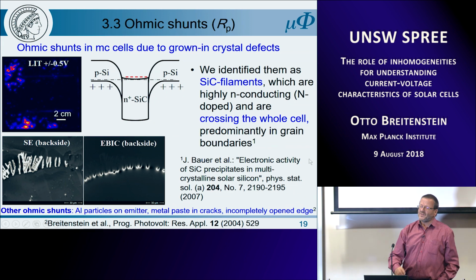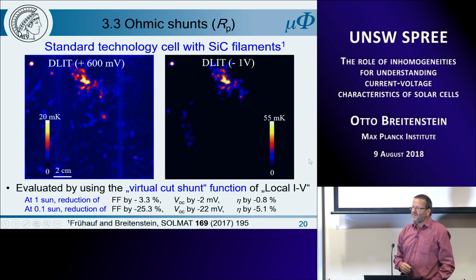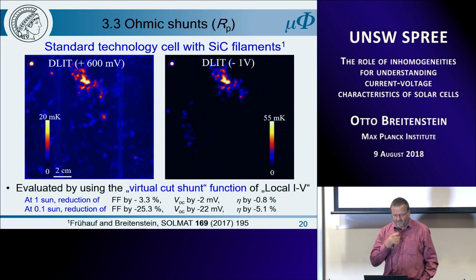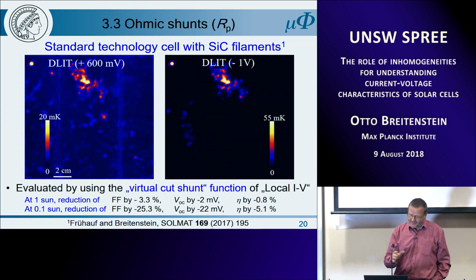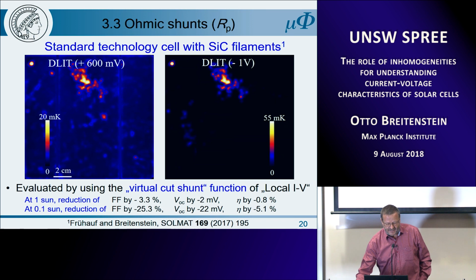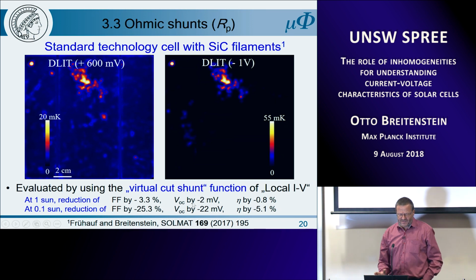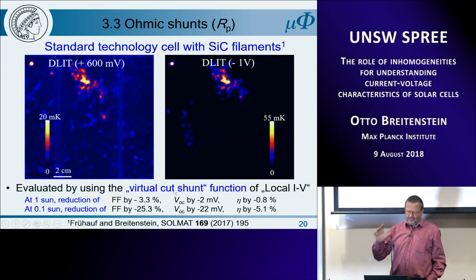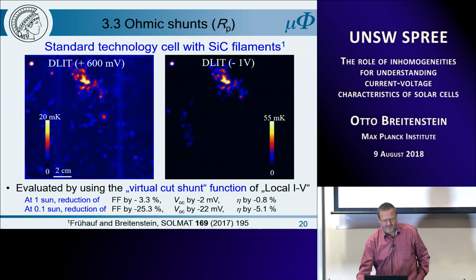So this is another solar cell, because the cells before didn't show prominent ohmic shunts. This was a shunted multicrystalline cell having this type of defects. And we have evaluated it using the so-called virtual cut shunt function, which allows us to replace the properties of a certain selected area by the properties of the surrounding. So we can virtually cut out the shunt and leave the cell intact, within this software.